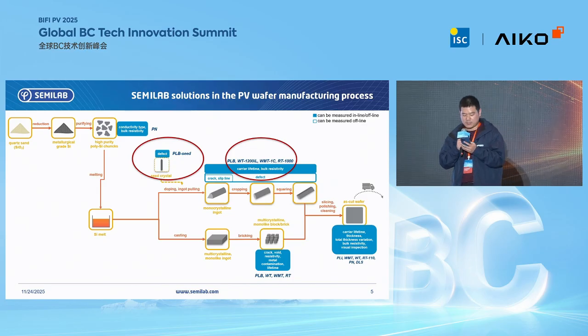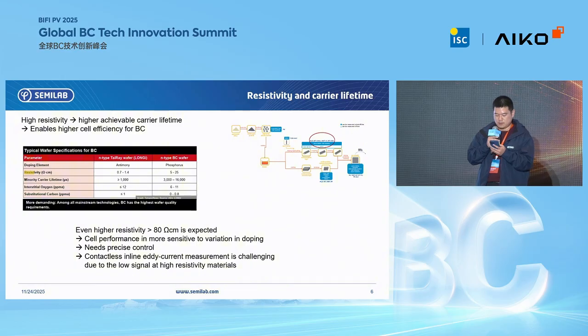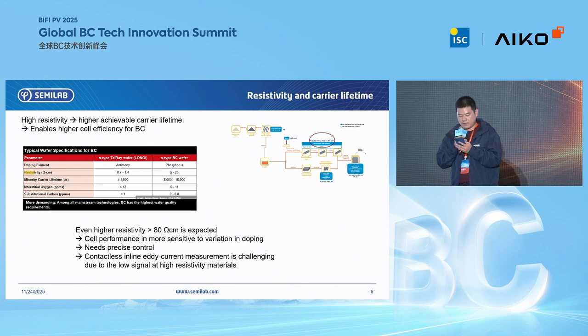Let's move to a rapid visualization of measurement techniques for the entire PV production chain. I highlighted, and I will present, the seed crystal testing, resistivity, and lifetime measurements for ingot manufacturing, where our company made significant developments this year. We know that due to the excellent surface passivation conditions achievable in BC cell architectures, further reducing the recombination rate in the wafer enables very high efficiency. However, in mass production, this requires reducing the doping concentration, say, increasing the resistivity.